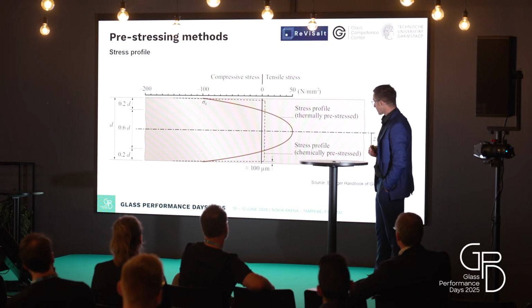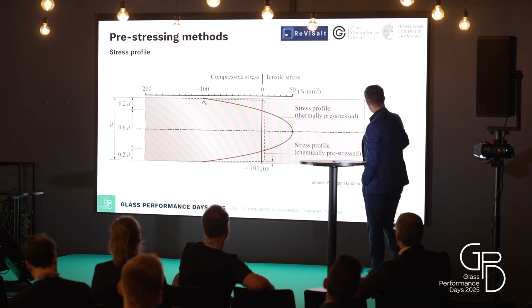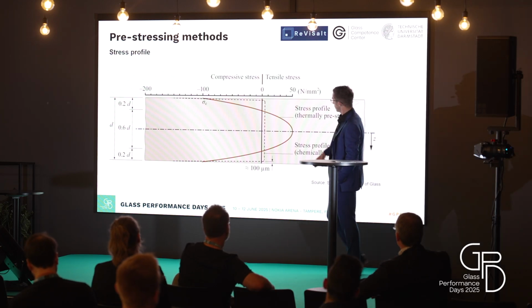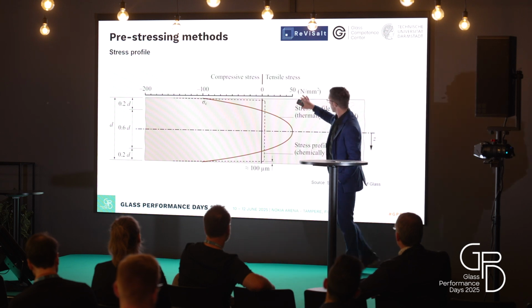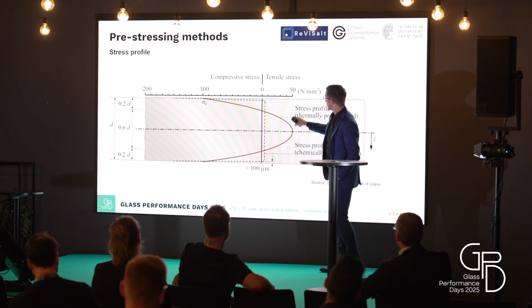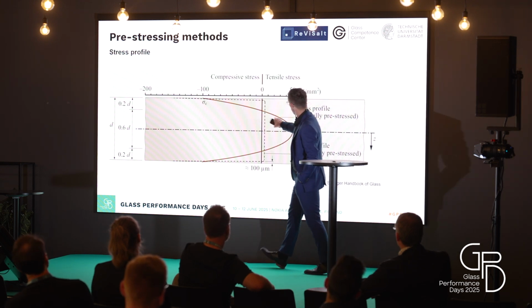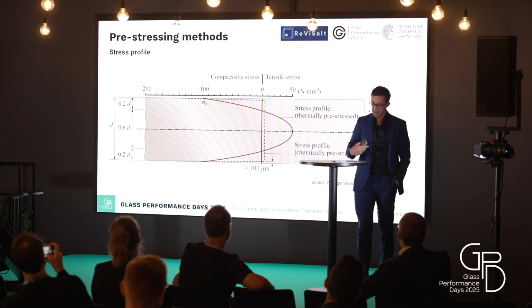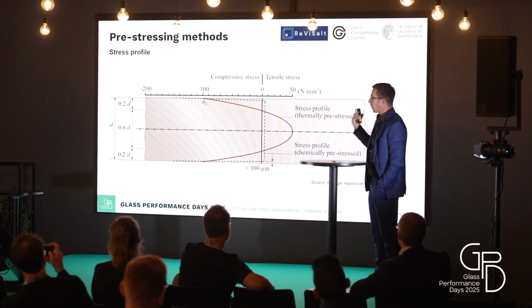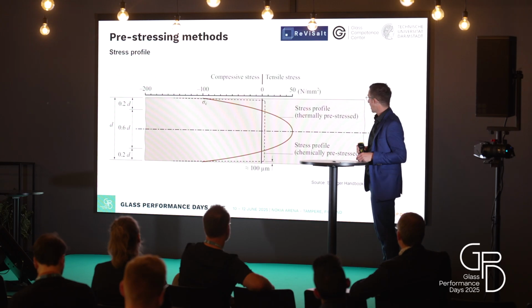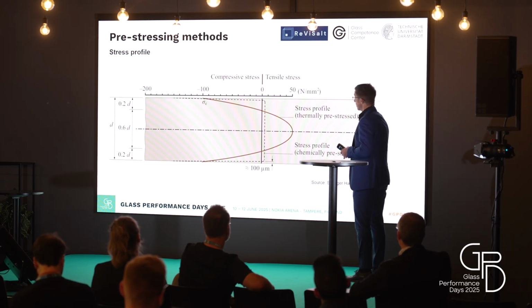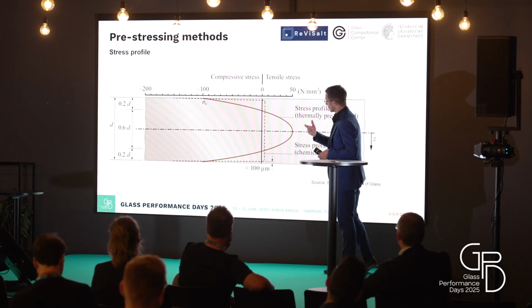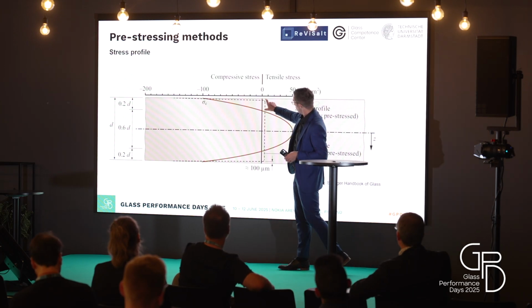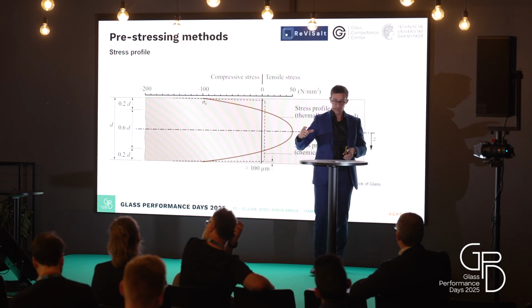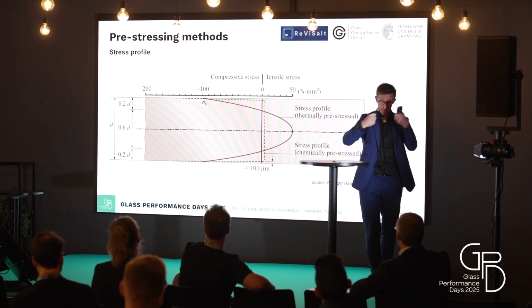Here you can see the stress distribution. This is the thickness of the glass. Here you see the compression part, the tensile part. This is the typical stress profile for the thermally pre-stressed part. Values more or less up to 100 MPa in compression. This is pretty good. It's also possible to go up to 200, but that's it more or less. And we have the big advantage: 20% of the thickness is under compression. This is pretty cool.